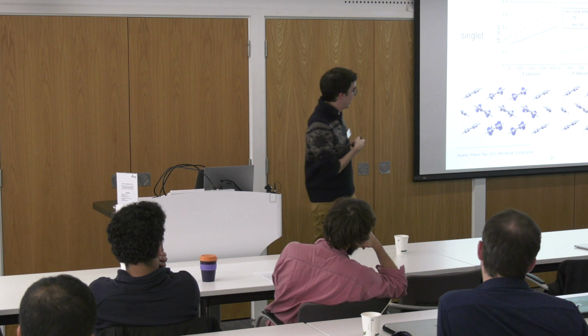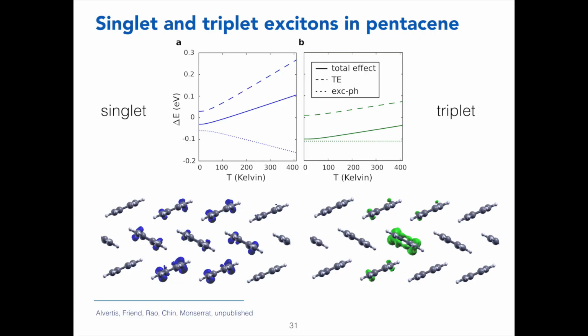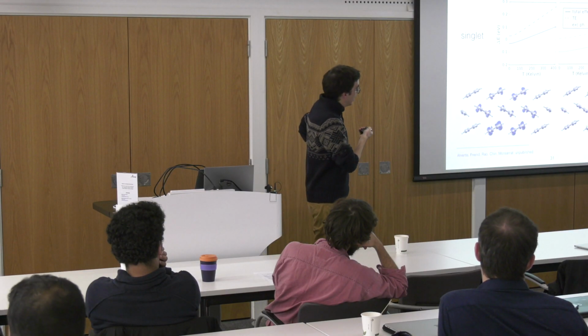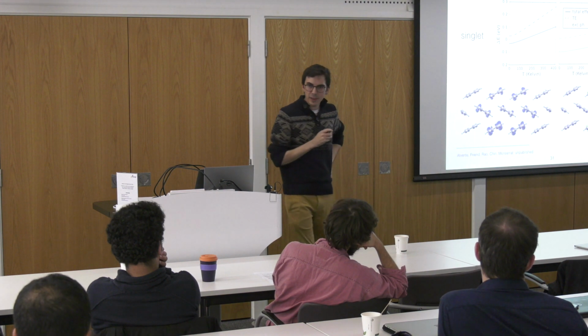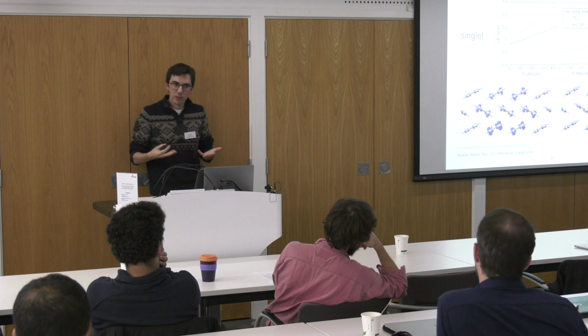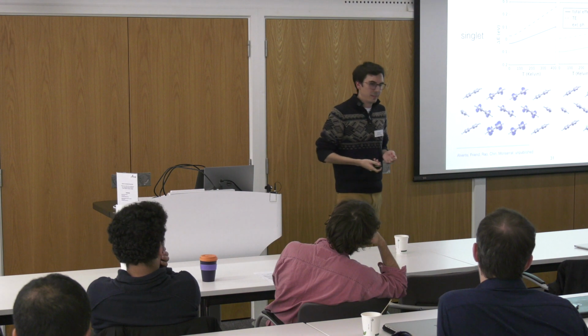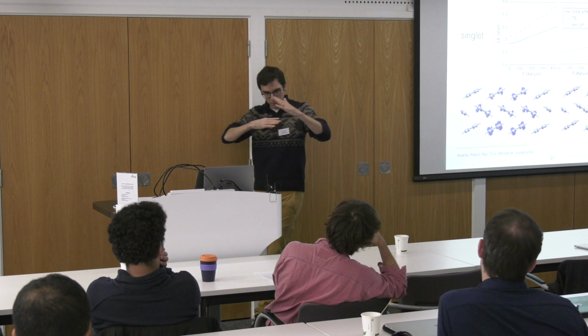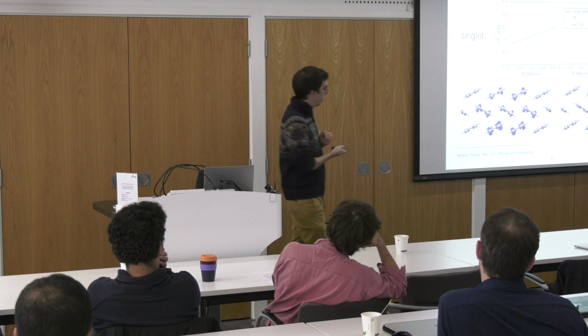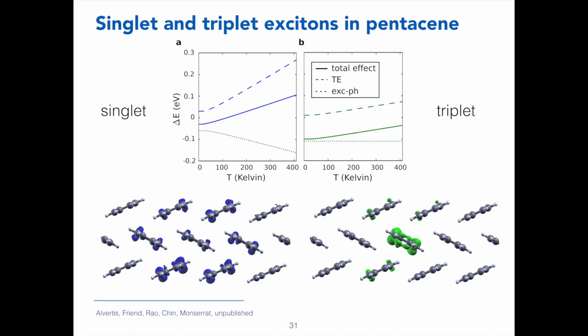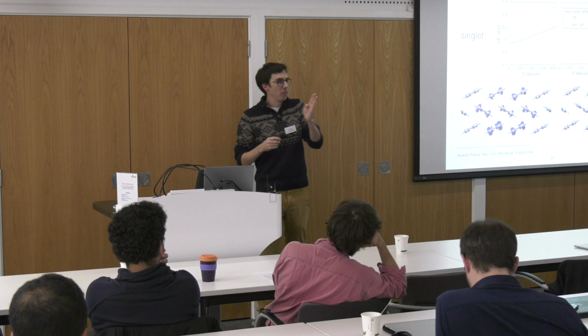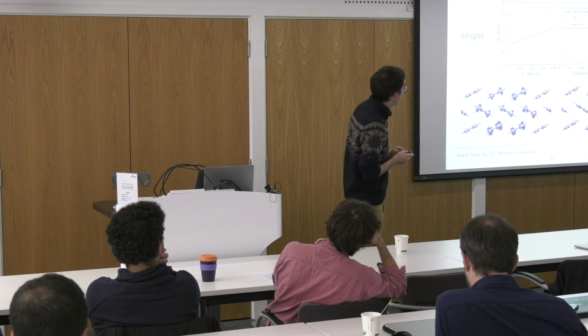The one I want to focus on in this talk is actually the exciton-phonon coupling. And you can see that if you compare that between the singlet and the triplet, the singlet has relatively strong temperature dependence, whereas the triplet has pretty much no temperature dependence. Now, why is that? That's because at the temperatures we're looking at here, from 0 to 400 Kelvin, the phonons that are exciting the system are low-energy phonons, and these correspond to crystal phonons in the system. So these are phonons that change the relative position of the different pentacene molecules in the crystal. Such dynamic disorder in the system will greatly affect an object like the singlet, which is delocalized over many such molecules, but won't do much to an object like the triplet, which is sitting on a single molecule, and therefore it won't really care much about the relative position of other molecules.